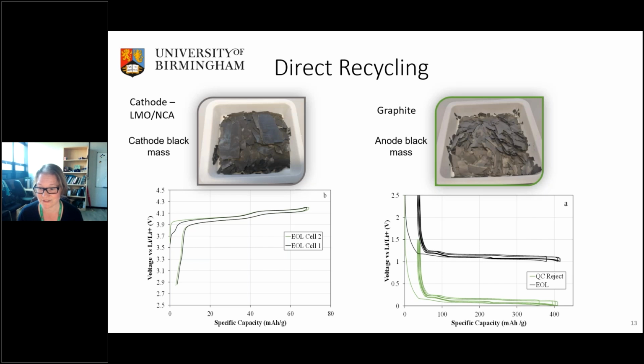The graphite itself, as you can see, we can reuse directly. And this gives you an example of the electrochemistry that you'd see from a rejected cell, QC reject, or end of life. And both of them give us pretty decent capacities. And then on the left-hand side is the electrochemistry that you would see from a cathode. This probably is about half the capacity that you'd want from a cathode. And this is because during the processing, a lot of the lithium is lost, and we need to put the lithium back into that cathode again before we can actually reuse it in this direct recycling process.